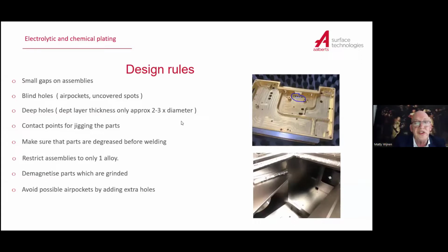Then deep holes: you must take into account that deep holes only have a coverage possibility of two to three times the diameter. So if you have a hole with a diameter of 6 or 7 millimeters, you can go in for 14 to 20 millimeters depth, and your layer is covered. Your product is covered, not more. Make sure the contact points are there.